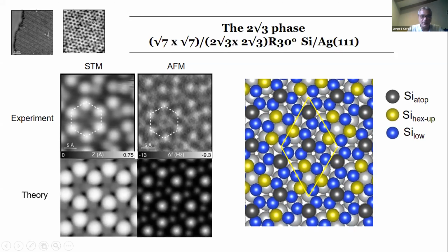Okay, when we do the simulation for this structure, we can get a very nice agreement with both the STM and the AFM images. As you can see, this hexagonal feature that we've seen here is associated with the bonds of the highest lying atoms, and these inner triangles, which can only be visualized in the AFM images, not in the STM images, correspond to the same kind of triangles we were seeing previously in the 4x4. Okay, this is this buckled hexagon.